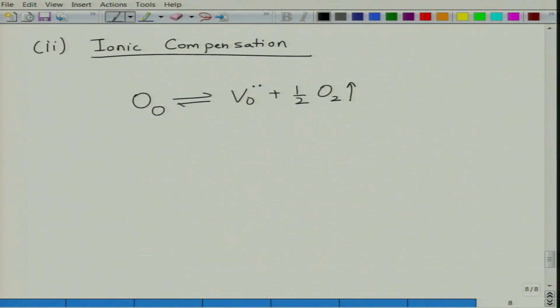Now, what may form is oxidation or reduction of the metal site, depending upon the charges. Here you have created two charges on the oxygen sites, which means the metal at the metal site will reduce. The two metal ions will reduce. In this case we are taking the example of MO2, so the 4 plus will become 2 plus or 4 plus will become 3 plus.